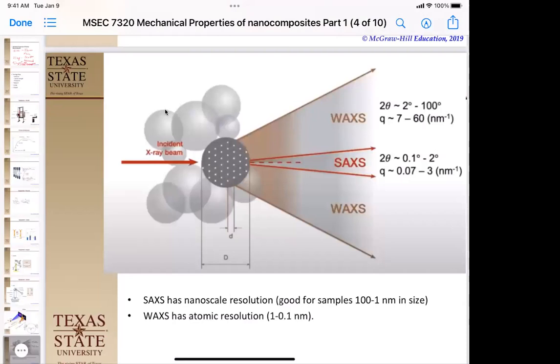Now, in the other one, we can have much larger agglomerates that will scatter in the wide angle scattering. So the difference between a clay tactoid, which is macroscopic, greater than that 100 nanometer scale, versus clay plates that are near each other. So you're going to see, ooh, tactoids, ooh, no tactoids, ooh, crystalline structure, ordered structure, or disordered structure. That's what we're really looking for when we look at X-ray. We're looking for dispersion and order or disorder, depending on which one we want. And again, it's a pretty easy tool to use once you get your safety training on it. And again, you can change the experiment from wide to narrow and get a lot of data.